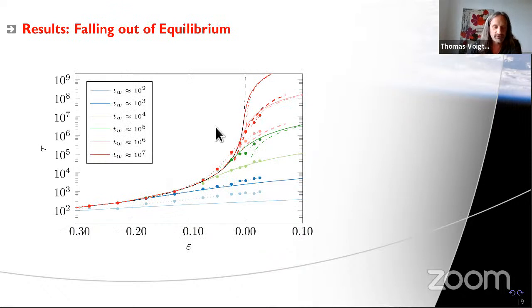Just briefly, here's the different representation, the one that I also stole from your papers, which is the relaxation time drawn for fixed waiting times for quenches to specific points. So this is basically a packing fraction here in terms of a distance parameter. If we look here, this would be for quenches to exactly the equilibrium glass transition point. And you see there's a black dotted line here that diverges. This is the equilibrium prediction, and again, it's either of mode coupling theory or of the self-consistent generalized Langevin equation theory.